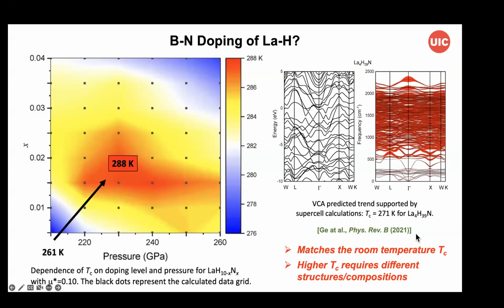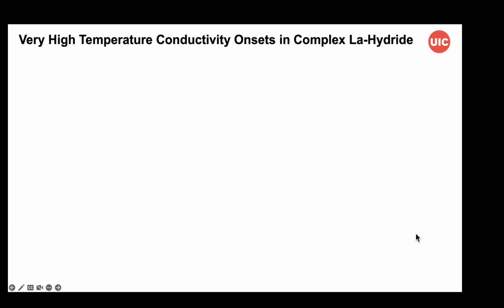This work was also followed up with supercell calculations, just as the work on CSH, and the supercell calculations, again, were limited by the size of the supercells for the Tc calculations, but we found for this supercell with 4 lanthanums, 39 hydrogens, and a nitrogen gives a shift in Tc that's more or less consistent with what we get in the VCA calculations. So at least some support for the virtual crystal approximation. And this also points out, and I'll come back to this, that higher Tcs require some other compositions or different structures going far beyond the LaH10 type structure.